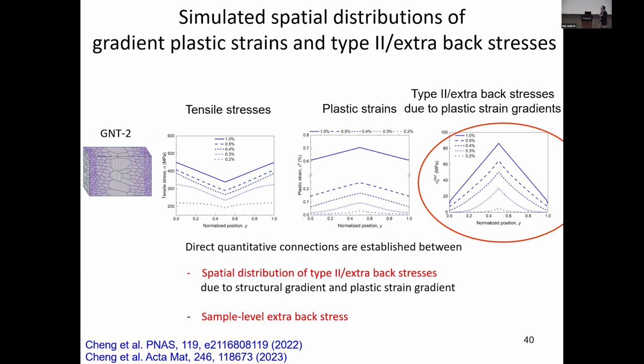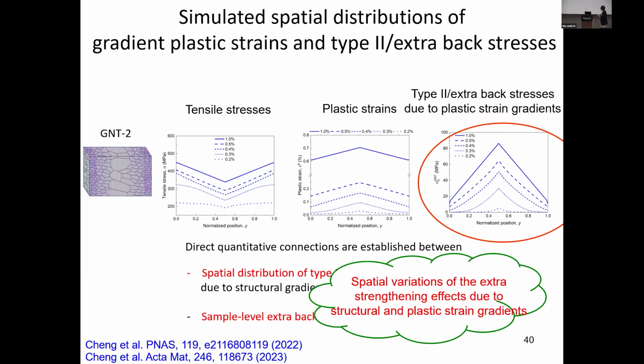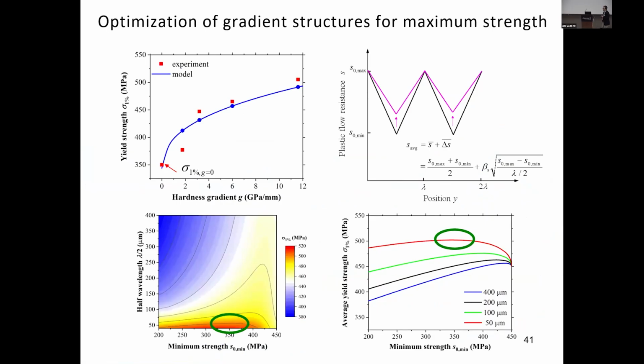contribution from different components, the local heterogeneity at the nanoscale, and the gradient structure effect across at the macro scale, so that we can understand the spatial and the temporal evolution of extra strengthening effect associated with this heterogeneous microstructure. So this enables us to further design this gradient microstructure to maximize this extra strengthening effect.